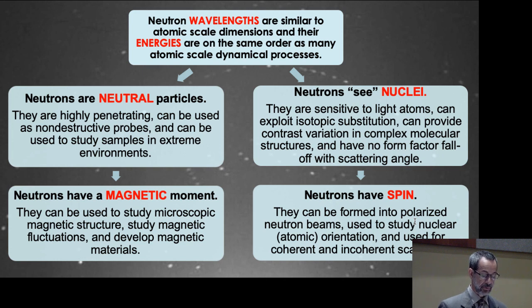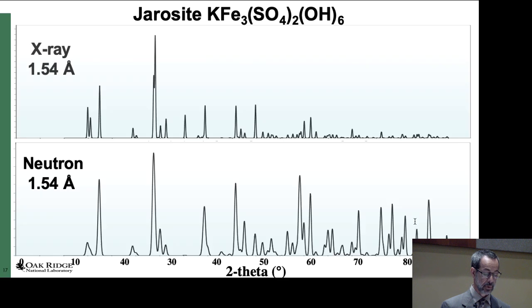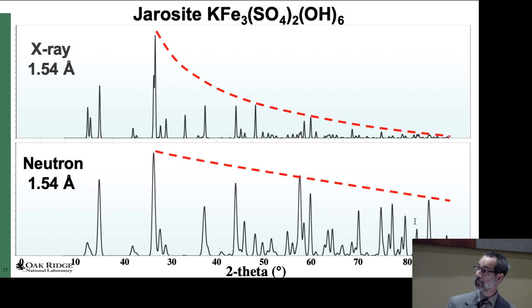What makes neutrons excel for structural and dynamical studies is that the wavelengths and energies match the length scales and energies of those fundamental properties of matter. Neutrons are neutral particles, they have a magnetic moment, they see the nuclei so have isotope sensitivity, and they have spin. We can polarize the neutrons. Contrast the X-ray scattering factor falling off with scattering angle versus none for neutron scattering, here for probably a Martian mineral.